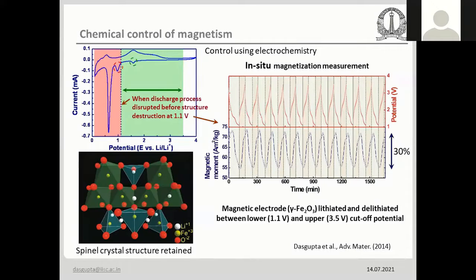And when we put such lithium ions inside, it is shown on the right hand side. This is an in situ measurement, electrochemistry. So that top right curve is the so-called charge discharge cycle, CP mode, chronopotentiometric mode. It's like a battery testing. But in the bottom curve, which is measured in situ in a PPMS magnetometer, you can see very nicely that the magnetic moment or magnetization is following this charge discharge. Excellent. And this is a 30% change at room temperature.